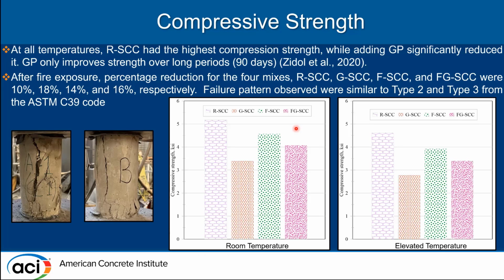On the left, you see the failure types for these cylinders. The types that we observed were type 2 and type 3 as per ASTM C39 code. And even after fire exposure, no changes in failure patterns were observed. They were pretty similar.